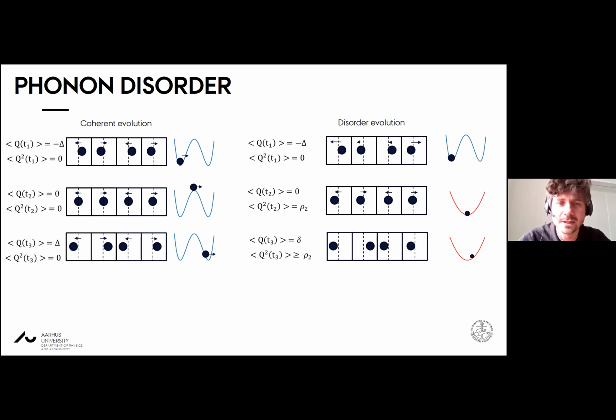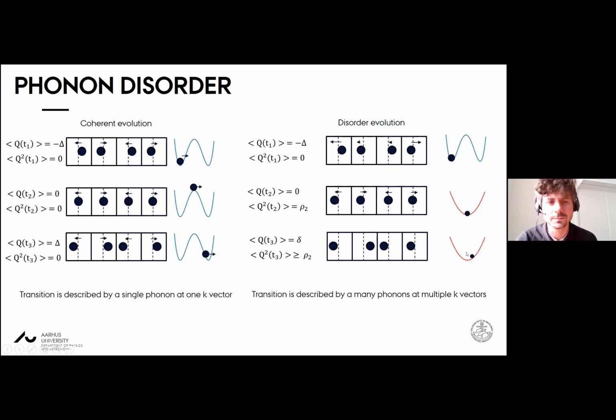And what's really happening here, which I've tried to draw with the size of the balls, is that the system is no longer really describable by this simple potential energy surface, okay? So in the coherent evolution, the system is described by a single phonon at one k vector, which is essentially what I'm plotting here, the free energy on the left-hand side. These blue lines would be as a function of a phonon at one specific k vector.